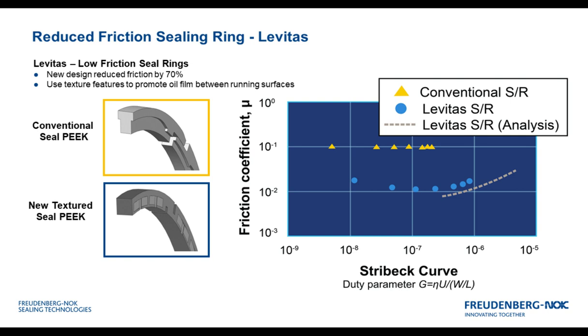The item below that in blue is a new textured seal, this Levitas seal. It has a shape that allows us to use fluid film to promote lowering the friction between the surfaces. And you can see from that one, it's much lower friction. We estimate about 70% lower friction. You can see it's already lower, and you can actually see the Stribeck curve where, as it hits a low point, it starts to see fluid shear, running completely on a hydrodynamic film.